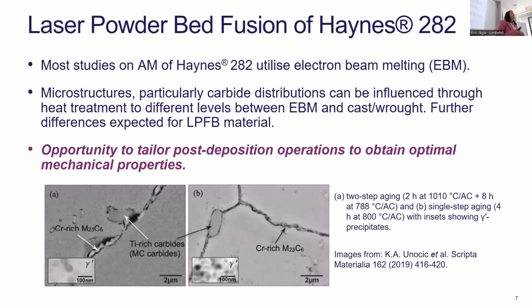So in terms of additive manufacturing of this material, at the time we were doing this study, there was very little on the additive manufacturing of Haynes 282. It was primarily just a few studies using electron beam melting. Since then, there's been a few more, but I'm bound by industrial clearance processes, which means that I can't update slides very easily. So we're sticking to the few studies that were available at the time. And one of the key things that was identified was that the microstructures, but particularly the carbide distributions, were quite different from the cast and wrought to the additively manufactured component. So one of the key things was the MC carbide and the M23C6 and where and how it precipitates through the material.